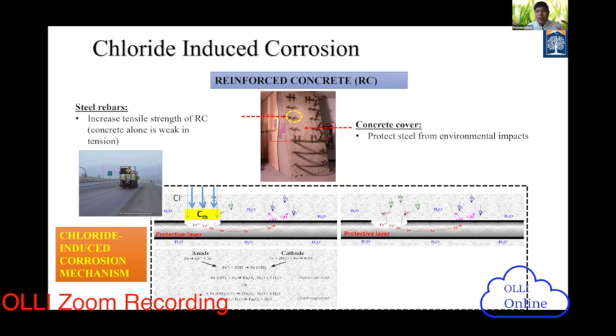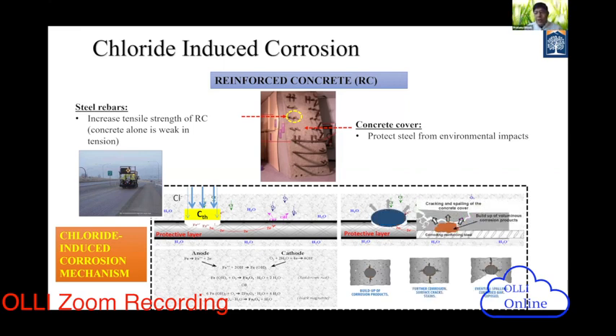Initially, the corrosion products, which is basically rust, were okay, which we are seeing from the anodic and cathodic products. As you see, they are forming compounds, basically red-brown rust and black magnetite. But after a certain amount of time, they get attacked by this chloride salt. So once the chloride salt attacks, the corrosion process starts to increase, as you see from the buildup of corrosion products. Further corrosion happens, more and more surface cracks develop, and then eventually spalling happens. That's basically the end of the service life.